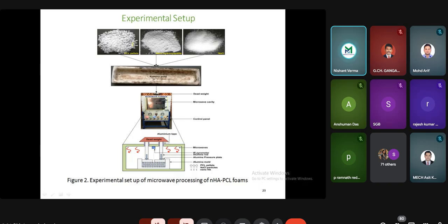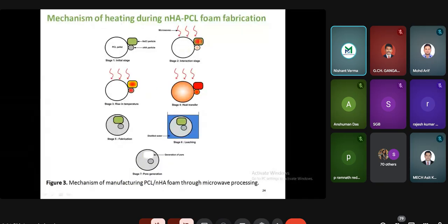So we put the raw material containing polycaprolactone, nanohydroxyapatite, and salt into this mold, and we put the mold under the microwave. So what mechanism happens in the case of these three materials? The NaCl, that is salt, has a higher dielectric constant compared to the polycaprolactone and nanohydroxyapatite. So firstly, the heat transfer takes place from the NaCl to the hydroxyapatite, then to the pellet.